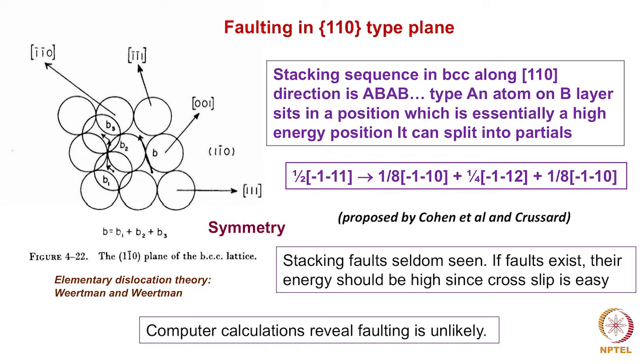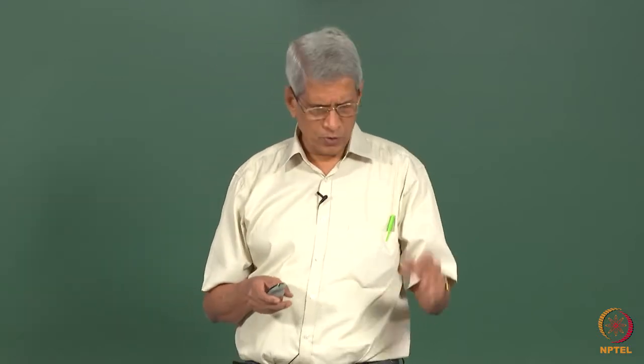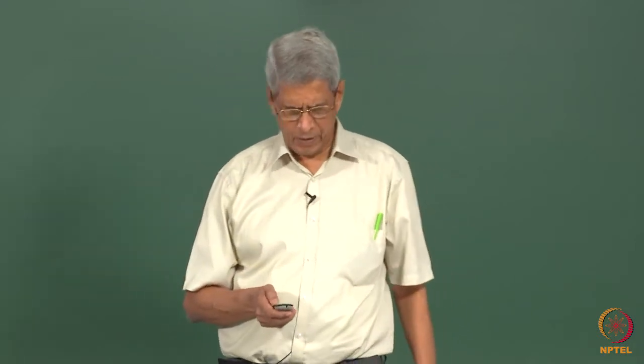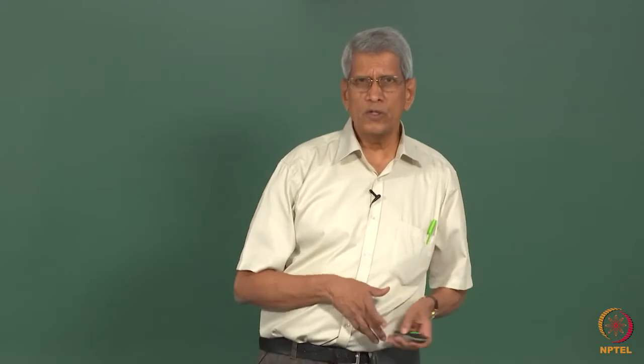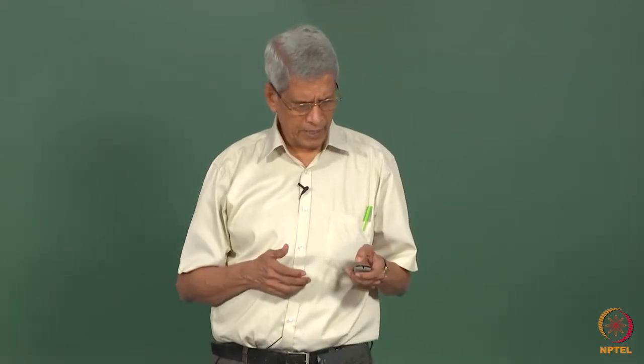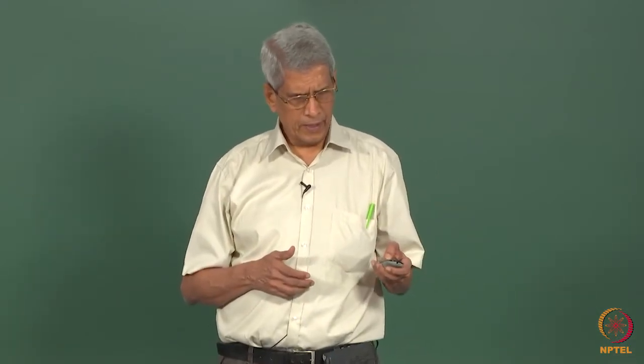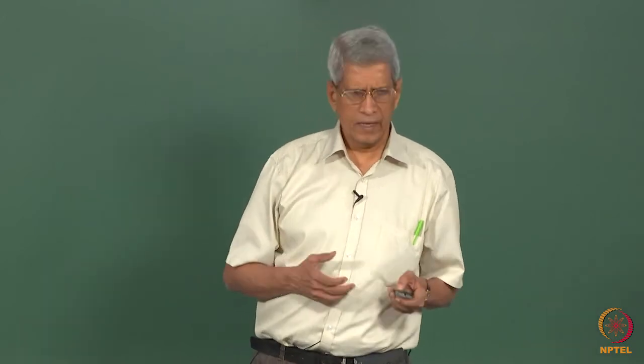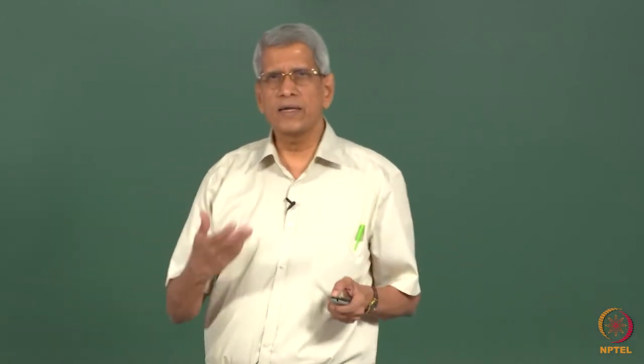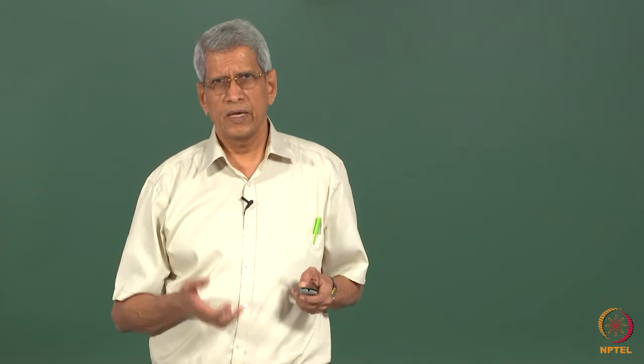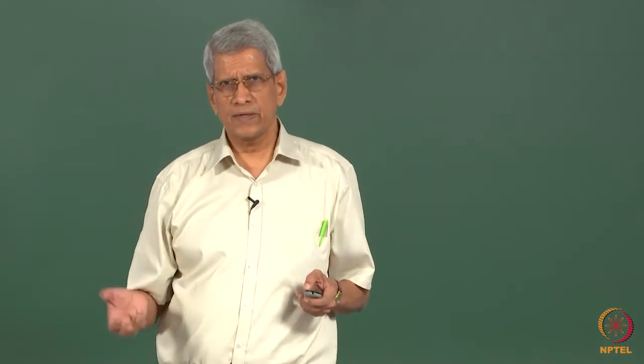Because of it, the movement of these dislocations should create a stacking fault, correct? But experimental evidence did not show any stacking fault in most of the BCC materials. They were seldom seen. So then they thought that the fault energy may be very high. Because of this, only cross slip takes place.